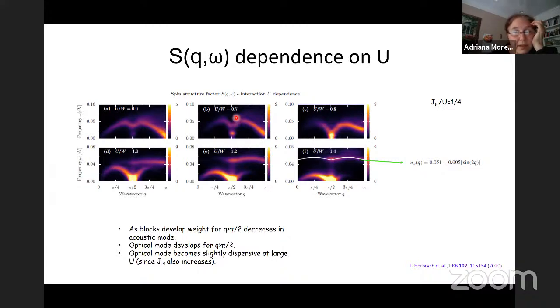But as the blocks start forming, we start seeing a spectral weight at pi/2. Then when the blocks are more formed, this spectral weight is more intense here. And once the blocks really form, we get the optical mode, and this spectral weight becomes much more negligible.